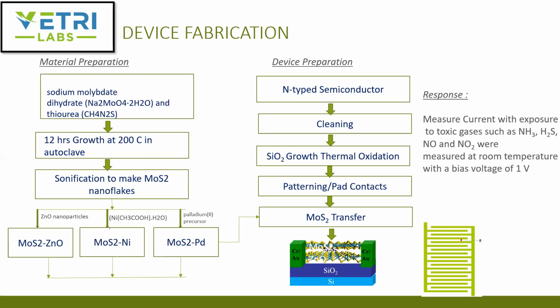And these are nano flakes. Then you can additionally functionalize them, depending on the type of material you want. For zinc oxide, you can add zinc oxide nanoparticles. For nickel, you can add a nickel precursor, a nickel acetate precursor. If you want to functionalize with palladium, you add a palladium 2 precursor. And you get each of these materials, which are then put on the device with the N-type semiconductor.